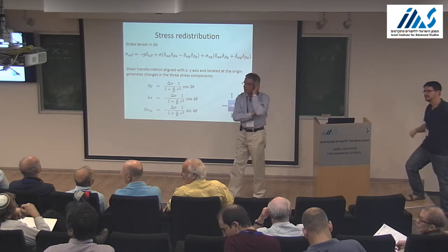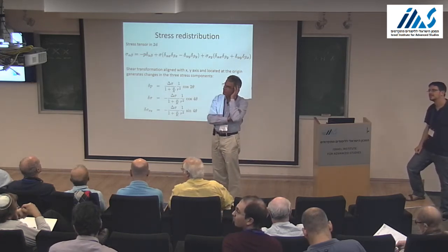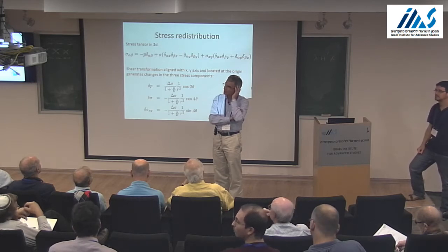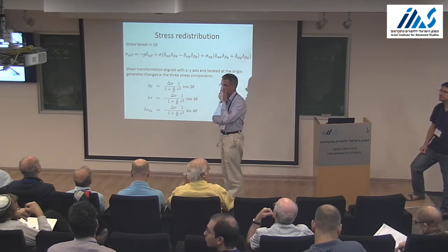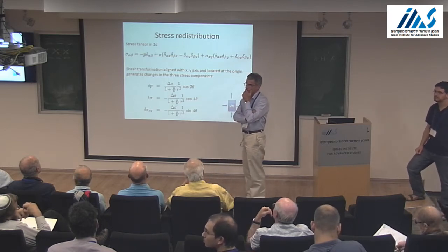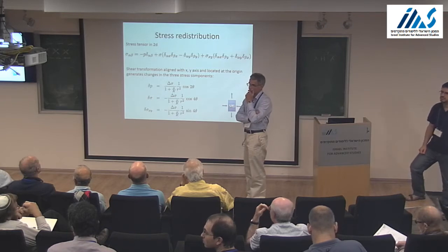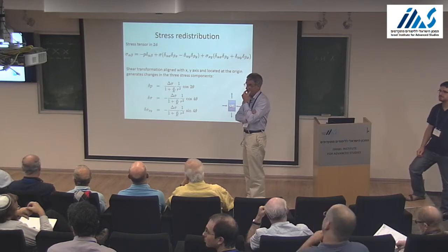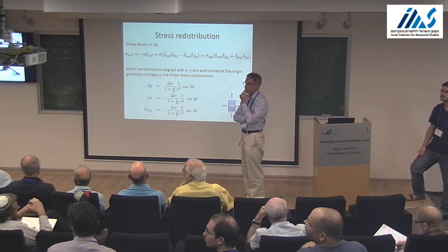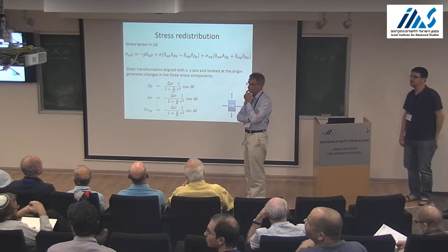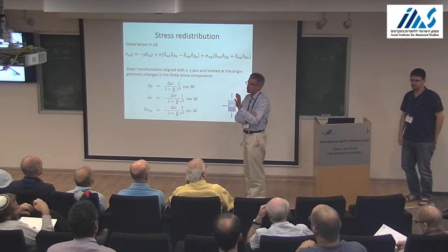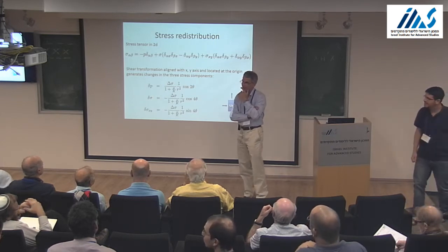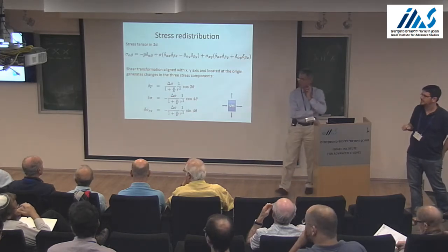The Eshelby solution is a solution in linear elasticity. If linear elasticity doesn't apply, then the Eshelby solution doesn't apply. Correct. And I presume the assumption is that the deformation of whatever medium you're considering can be characterized by linear elasticity, that the elastic energy dominates. Exactly. If that doesn't hold, it doesn't matter whether it's Eshelby or some other solution. But in the far field, it should always be right, because in the far field, it should be linear. It holds on all scales.